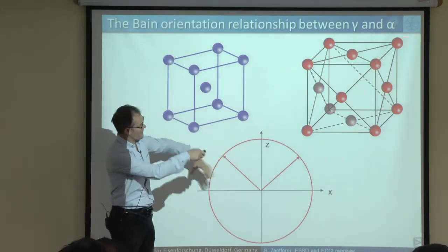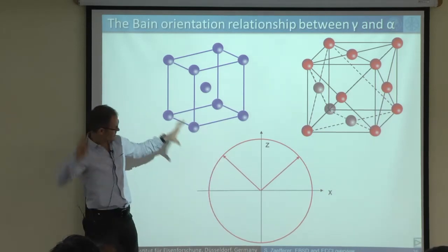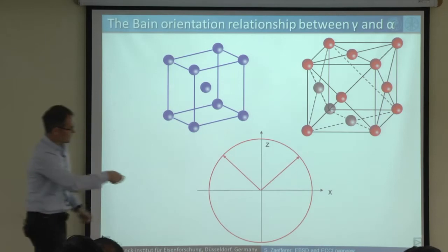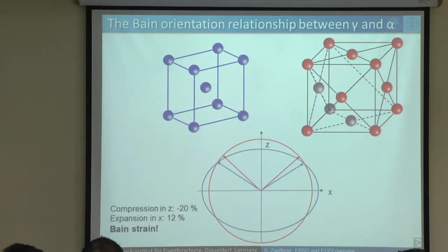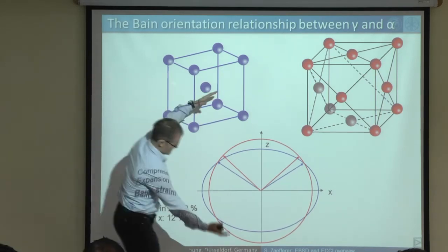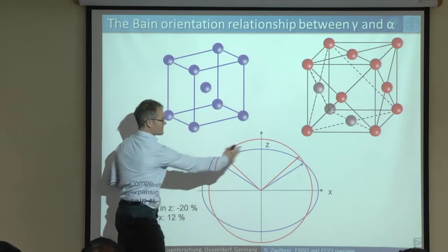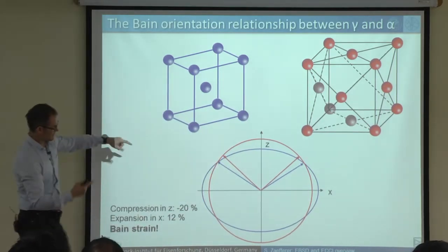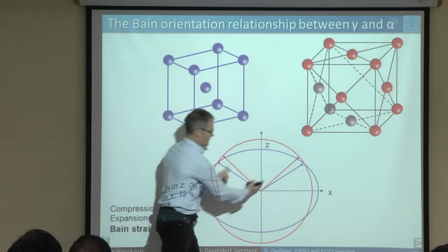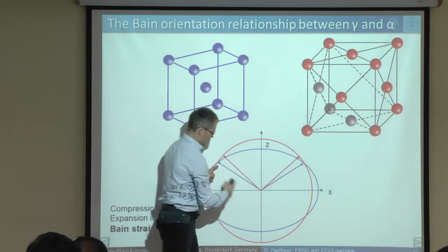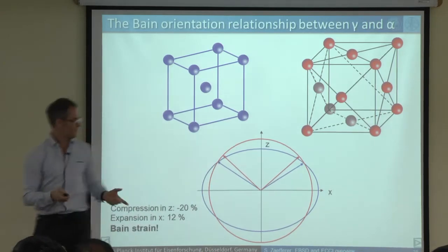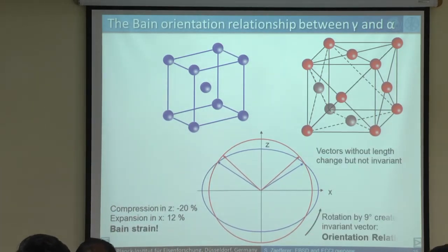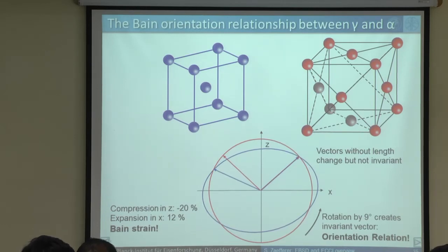You have the austenite depicted as a cube, as a sphere. And this austenite sphere needs to be compressed into a ferrite sphere. Yeah? And of course, when you just compress this, you will get an ellipsoidal distortion. And the atoms, the atomic or crystal positions indicated here by these red arrows and the blue arrows, they don't fit together any longer. So in order to make them fit together, you need to rotate one of these lattices so that at least one of the two arrows fit together. You have an invariant line, and the others then are not fitting together.